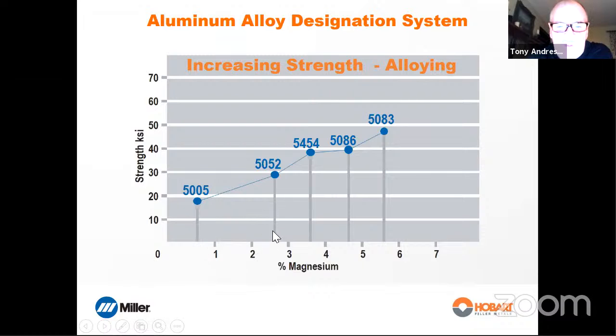As we increase the magnesium, we go to 2.5%, we get 5052, which is a very popular alloy. You use it for fuel tanks. It's very formable because it has relatively low strength and great ductility. And it runs in about here. And then we can add more magnesium and we get 5454 with slightly more strength. Actually, that needs to come down a bit, and it needs to go over here a bit. But anyway, I'll have to fix that slide. But the example is good. It's a good representation. We've got 5086 here with slightly more mag, slightly more strength. 5083, slightly more strength, slightly more mag. So we can see as we add more and more magnesium, we get more and more strength. So that to me is a pretty good example of how alloying assists in strengthening certain alloys.